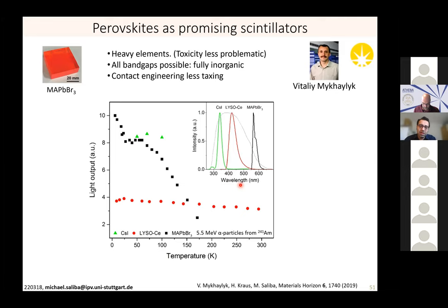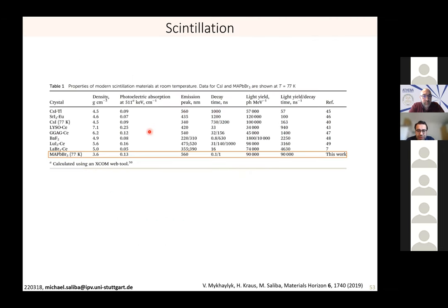And we started looking into perovskites in terms of their scintillation properties at low temperatures, and going very low here, this black curve compared to green and red, which is cesium iodide or LYSO, these are established scintillators, shows that perovskites at about nitrogen temperature can have a light output similar to commercial scintillators. And this is not even optimized yet, this methylammonium lead tribromide crystal. And this gives rise to the idea of cryogenic perovskite scintillators, for instance, for medical applications. And let me just give you a table here. A good scintillator is contingent on it having a high light output.